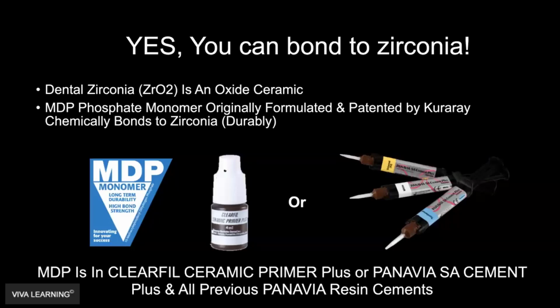It's MDP. Now, the great thing about this Clearfil Ceramic Primer, which comes in the V5 system, is it has silane in it and it has MDP in it. So if you need to use this for multiple things, you can. So we need to find MDP. And the other great thing is when we talk about the Panavia SA cements that are out on the market, there's MDP in there. So you don't have to take a separate primer if we're going to be using this Panavia SA system. It's built into the cements already. And as we add the MDP, the strength of the cement to the zirconia restoration increases as well.